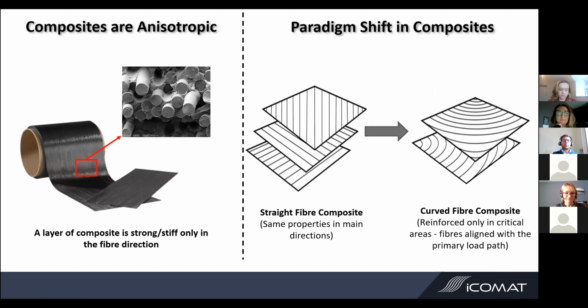So how are composites used at the moment? That's part of the issue. Composites, as you know, are anisotropic, so they're extremely strong in the fiber direction, strong and stiff, not so much in the transverse and through thickness directions. So the way we use them at the moment is we stack layers of straight fibers to form laminates which have roughly the same properties in every direction. Whilst this works and it's really good, it's by no means the most optimized way of using composites. So what we're proposing here is that if you use fiber steering and curved composites, you can really align the fibers with the load paths in your structure, and that way get the most optimized structure possible.